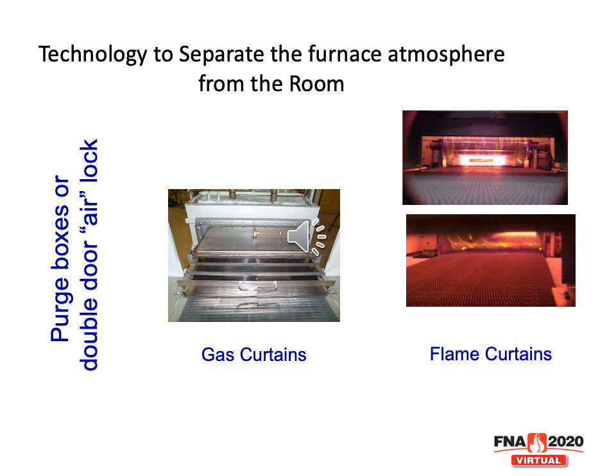We fill a box with hydrogen and nitrogen before opening the internal door to the furnace, so you're not putting air within that furnace. There are gas curtains for separation from the outside to the inside, and they usually have stacks of some sort within the furnace to help control the airflow, like the Venturi I mentioned earlier. They use it for binder removal and for hydrogen burn-off stacks. Some hydrogen furnaces use flame curtains that act as a barrier to stop oxygen from entering the furnace and hydrogen from getting into the room.